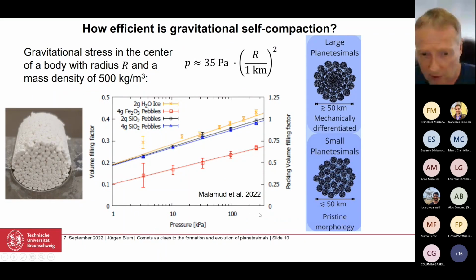And we exerted compression, pressure, and measured the filling factor, so the density basically, of that pebble pile. And you see a relatively linear-log relation: pressure is in log units, so a logarithmic increase in the volume filling factor or density as the pressure increases. And we can compare the artificial pressures we apply in the lab with a real lithostatic pressure, which is 35 Pascal per kilometer radius, but the radius goes squared into the whole calculation. So at the end, if you do the math, we end up with large planetesimals destroying the pebbles because the filling factor goes to unity, so the pebbles are gone. Whereas in small planetesimals, the pebbles completely survive.